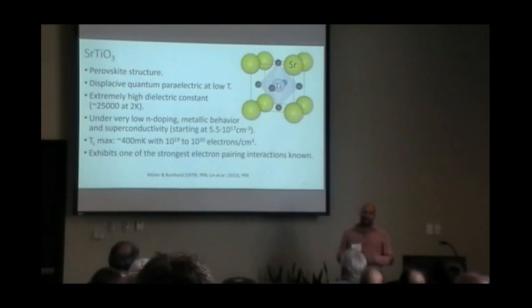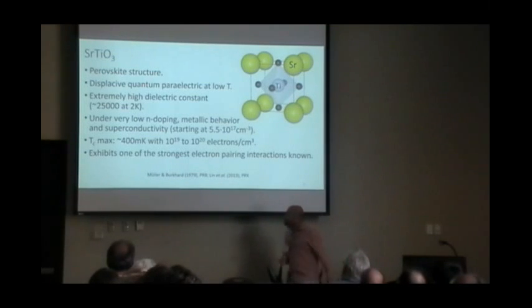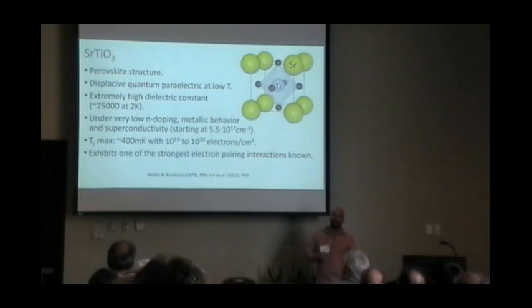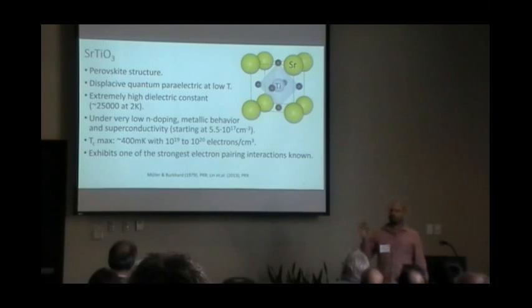So you can easily metallize the normally insulating material with a very low number of dopants. This is already very interesting, but what is really surprising is that it becomes superconducting at extremely low electron densities of 5.5 times 10^17 per cubic centimeter. And then if you put in more dopants or more electrons in a different manner, then you will reach a maximum TC of 400 millikelvin, and then it will drop again. So you have something like a superconducting dome.